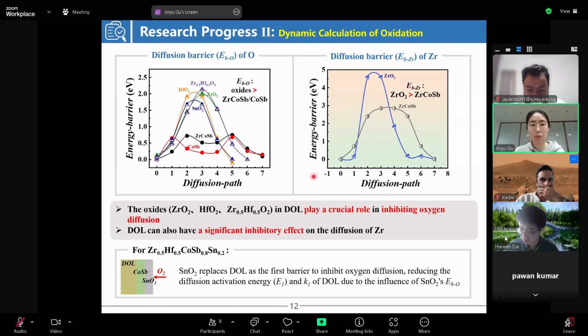And as for the barrier layer, I think it is more important to the kinetics. Later I did some study on the influences of the dopants on the oxidation behavior or oxidation rate. And there is some doped zirconia in the DOL. So I use the energy barrier, the diffusion barrier, they are different, and they can help me to explain or predict the oxidation rate or diffusion rate of oxygen in the DOL.